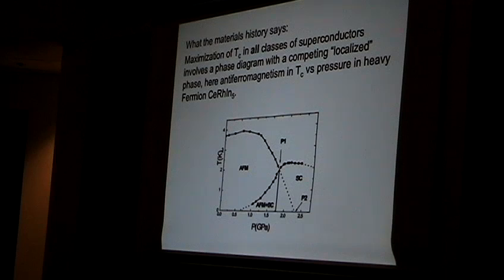In the case of heavy fermions, it's some antiferromagnetic phase versus pressure, as shown in this particular phase diagram. This is actually from Tuson Park. This is CeRhIn5 under pressure. The interesting point here is that when the antiferromagnetic phase boundary intersects the superconducting phase boundary, the magnetic phase boundary does not extend into the superconducting side. Namely, superconductivity actually takes out the antiferromagnetism.